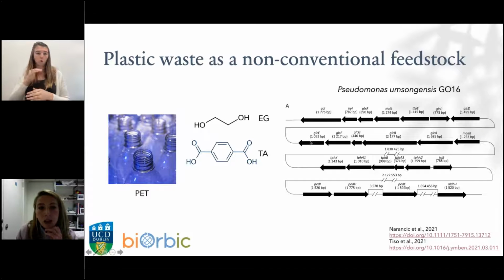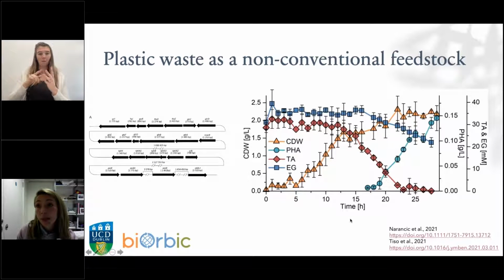terephthalic acid. Because Pseudomonas umsongensis can grow on ethylene glycol, but not so great, we then subjected this bacterium to adaptive laboratory evolution, in which we were offering this bug increasing concentrations of ethylene glycol, and we were selecting for fast growers. And by that, we were able to get an evolved strain that was able to use both ethylene glycol and terephthalic acid at the same time and grow well, you can see here with this orange curve, and accumulate PHA.